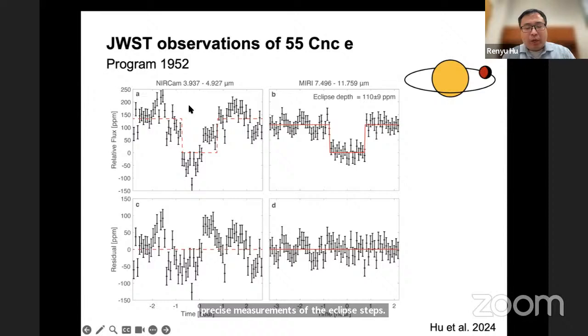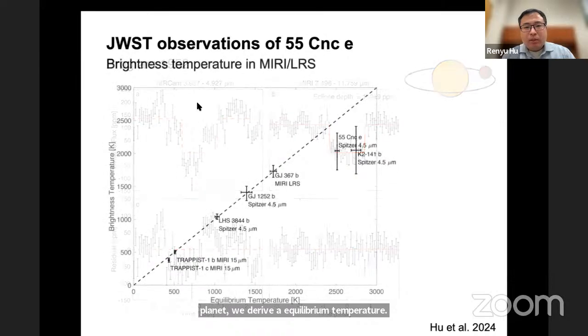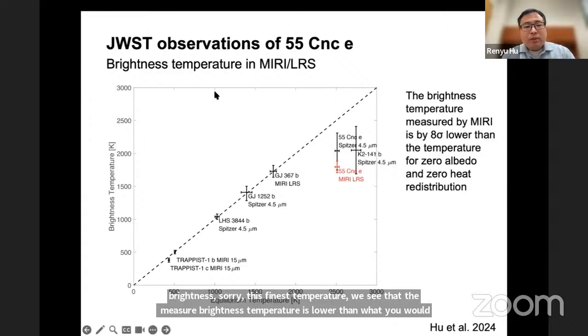So based on the eclipse depths, which measures the thermal emission flux from the planet, we derive a brightness temperature from the MIRI bandpass. And if we put that temperature on this plot, we see that the measured brightness temperature is lower than what you would expect for a bare rock planet by 8 sigma. And this by itself means that the planet cannot be a bare rock, and instead must have efficient energy transport from the day side to the night side, which lowers the temperature, or it could have gas absorption in the MIRI band that lowers the brightness temperature observed in that band.